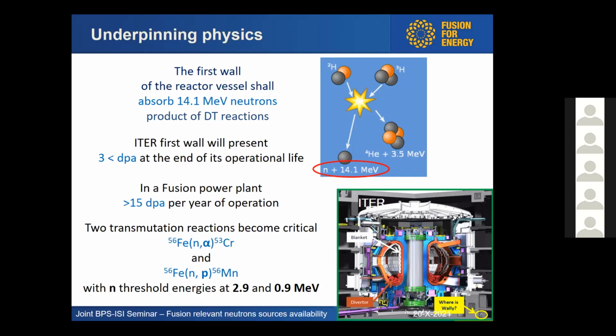And in fact, the main problem in structural materials is that there are two reactions on iron with threshold energies, typically above the average energy of fission reactors. The one which transmutes iron into chromium, liberating an alpha particle, has a threshold energy of 2.9 MeV. There is also another transmutation reaction in which iron absorbs a neutron and liberates a proton, transmuting into manganese. So basically, the structural materials which are based on iron, steels, lose their nature. And the alpha particle, which, as you know, is helium, becomes a gas in the lattice of the material.